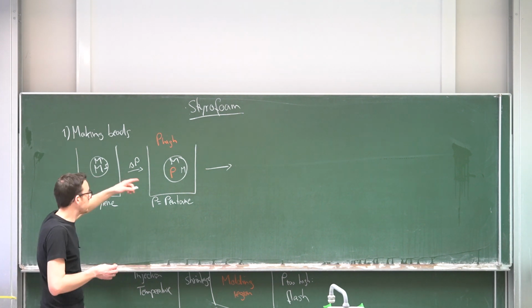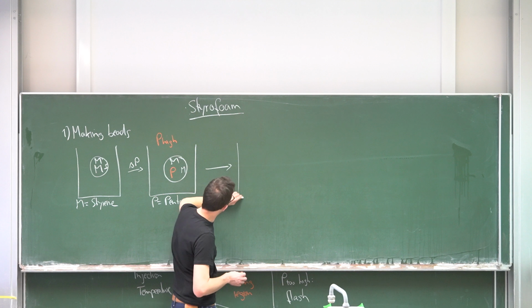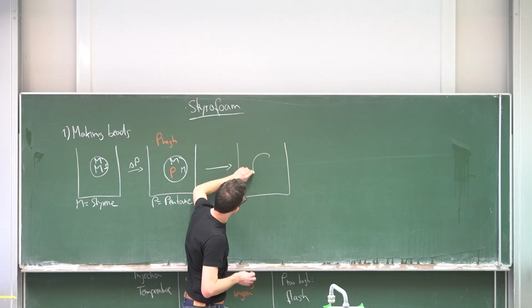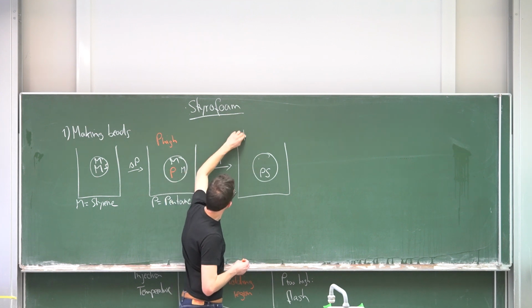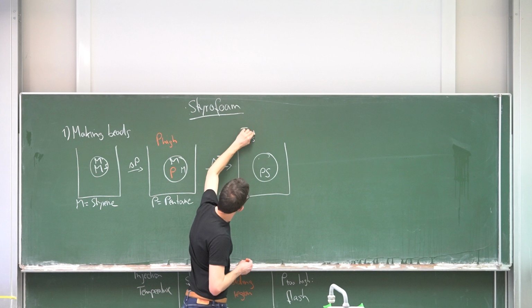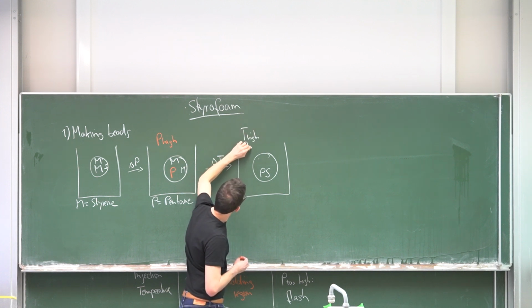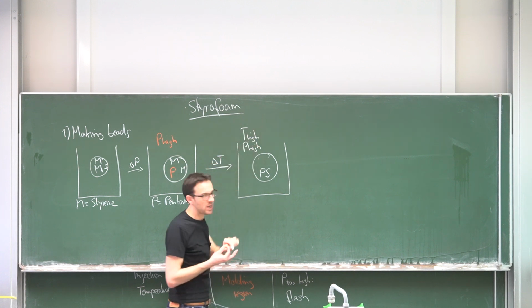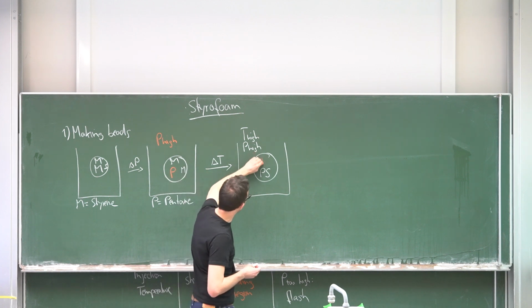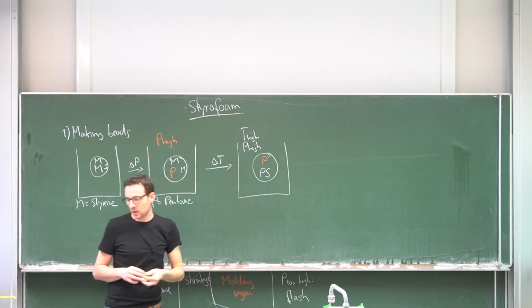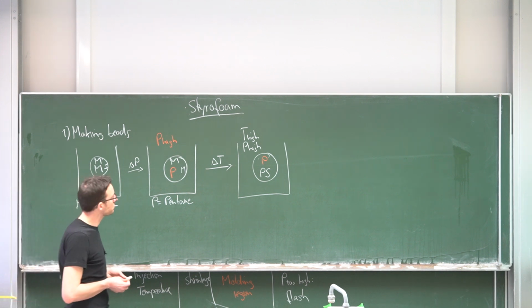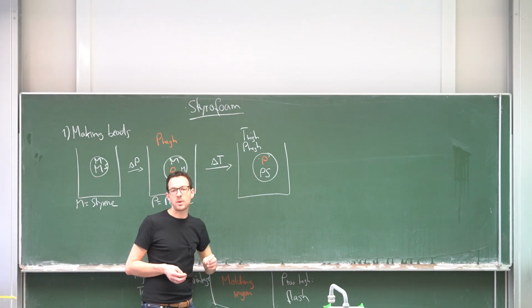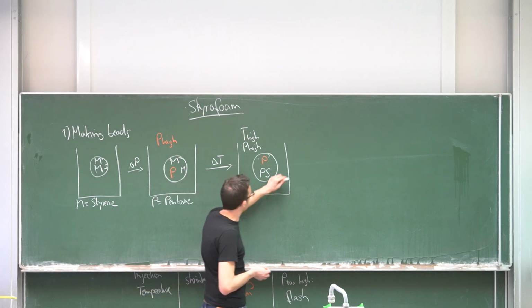You now initiate and you form a PS bead. So now T is high and P remains high, and this still contains pentane. And simply because the pressure is high, the pentane stays in there.